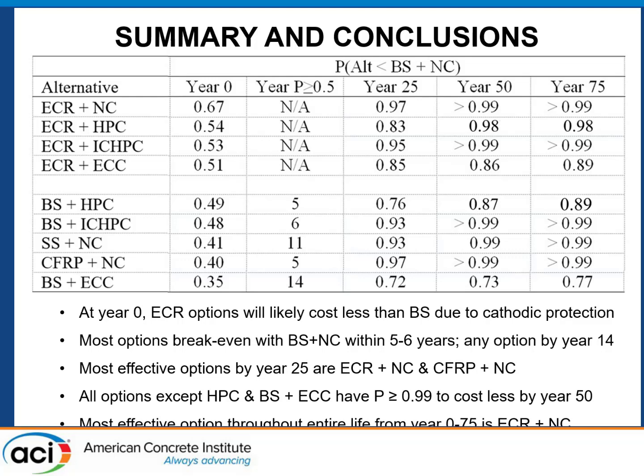By year 25, the most effective options in terms of probability to cost less are the normal concrete and epoxy-coated bars, shown at the very top at 97%, and the CFRP bars and the normal concrete also at 97% near the bottom. By year 50, all the options except for 2 have greater than a 99% chance to cost less.